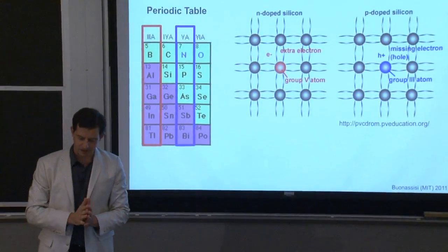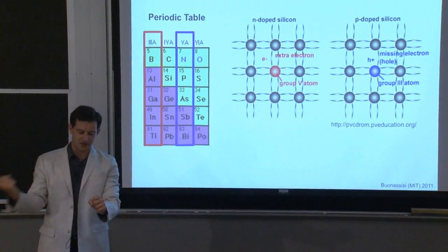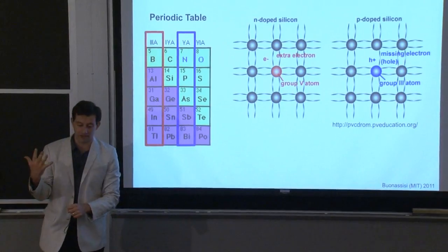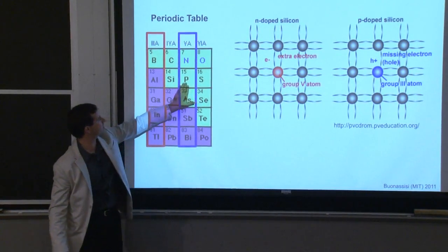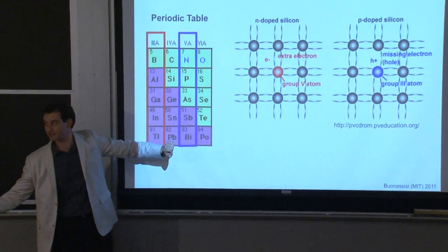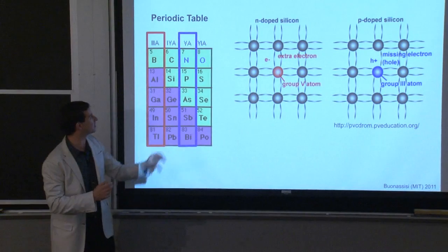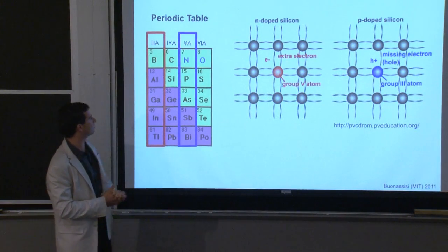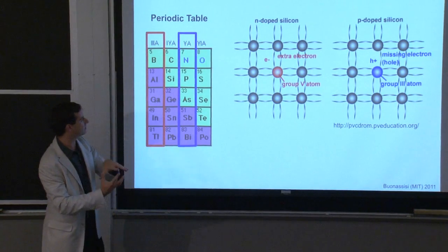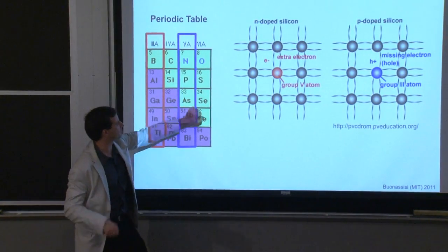So you can envision that if you were to introduce an atom and substitute out one silicon atom in that lattice for something else that has 5 valence electrons, such as phosphorus, it's almost of equivalent size. So those materials scientists in the room, from the Hume-Rothery rules, you should be able to estimate that the miscibility is rather large. In other words, you could mix in a high concentration of phosphorus into your silicon, given the similar size and similar atomic structure, electronic structure, rather.